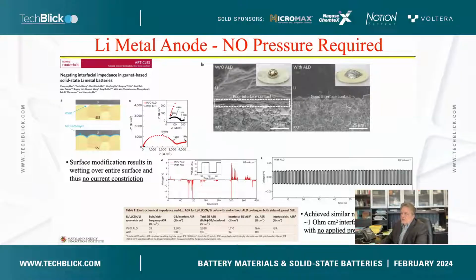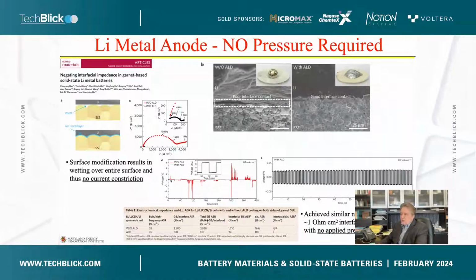The impedance here shows the data in red is without the surface modification, and the data in black is with, so we have to expand the scale there. Below that is the cycling at 0.1 milliamps per square centimeter. Without the surface modification, you get very, very large voltages to try to cycle. But after the ALD treatment, it looks like a straight line. If you blow it up, you can see the square wave on it. We get interfacial impedances on the order of about 1 ohm centimeter squared, again at room temperature with no applied pressure.